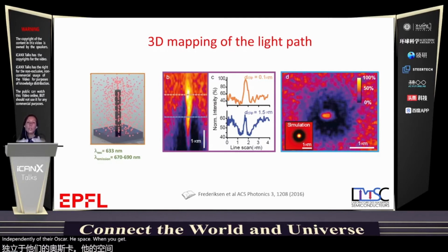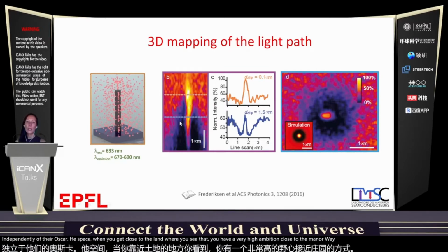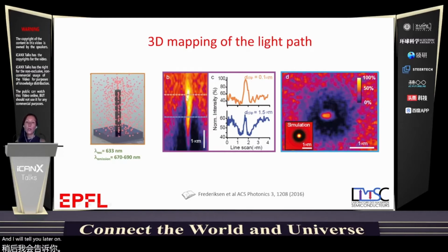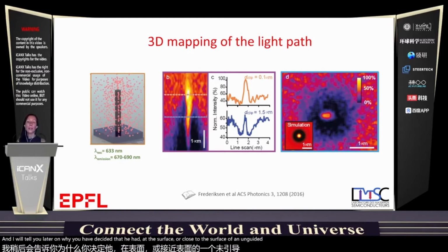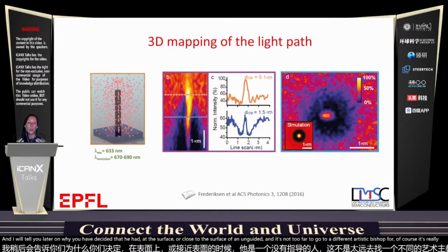Once you get close to the nanowire, you see that you have very high emission close to the nanowire, and then you develop some kind of shadow. I will tell you later on why you have this high intensity at the surface of the nanowire, and it's not due to a different distribution of the fluorophores. It's really due to the photon field.